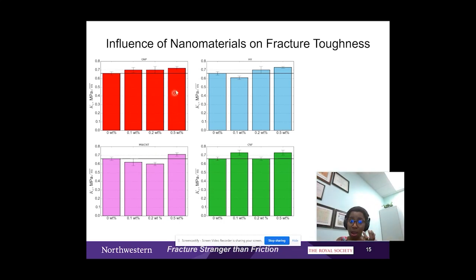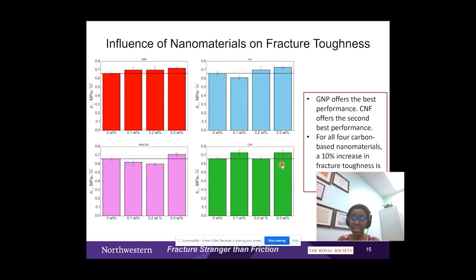One thing that is very remarkable is that when it comes to 0.5%, for all 4 types of carbon-based nanomaterial, we have a 10% increase in the fracture toughness. So this means that the procedure that I presented is really important and enables us to significantly improve the fracture toughness of cement nanocomposite.